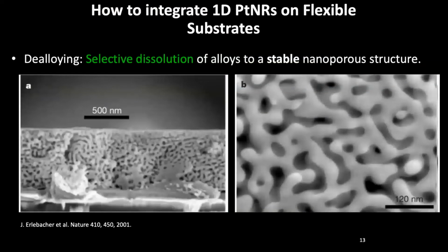And then to increase the surface of platinum, we were inspired by this work that allows us to do nanoscale structures or high surface area structures with a low temperature process that's suitable to be made on flexible polymer films. So this is essential so that you can respect the thermal budget of the substrate. This process is called de-alloying, where an alloy of silver and the metal that you need for, in this instance, what we're seeing here is gold, and we applied it for platinum.